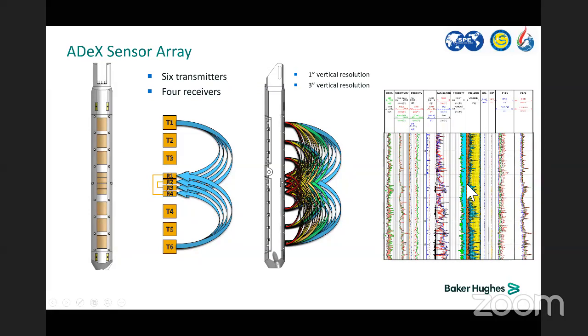And also you can identify your M and N, the texture exponents, from the dielectric. So this tool is helping you when the resistivity is suppressed. The dielectric can help you get hydrocarbon saturation resistivity independent and Archie constant independent.